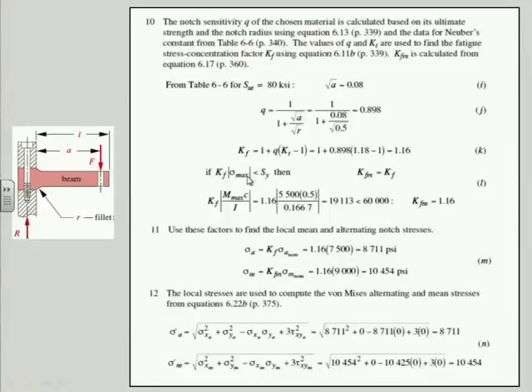So here we have to ask ourselves if this KF times the maximum stress that I happen to have, using the 5500 moment, is less than SY, then I'm going to use the whole value of KF. So I do that calculation. Take the KF, which I just figured out at 1.16, take the maximum moment, which was 5,500 inch-pounds, multiply by the C, divide by the I, and I get 19,000 and change. My SY for this material is 60,000. So I'm never going to yield in the notch. I think that's a good thing. I'd much rather be below the yield point in the notch, because then I'm not going to start growing cracks.